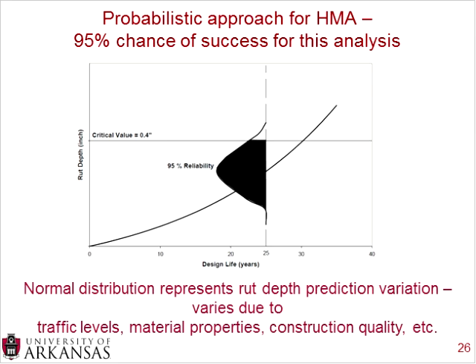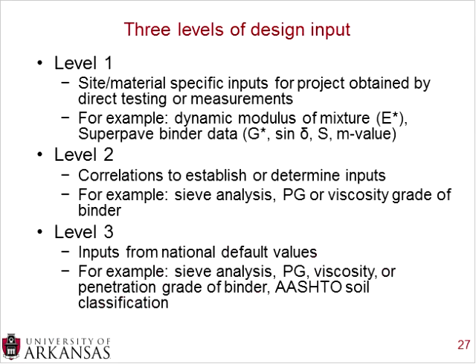Now that line goes through 25 at one point, but you can construct a 95% reliability curve around that. So you're 95% sure that rutting will be between or underneath that curve, and that looks like a critical value. If it's a linear scale of approximately 0.2 to 0.4, you're 95% sure that it will be under 0.4. So if you're willing to accept as a designer the 95% reliability, then this seems like a good design. And this normal distribution, how does it get created? What determines the amount that it spreads? Well, it varies due to your traffic levels, your material properties, your construction quality, and those other inputs that can be put in there.